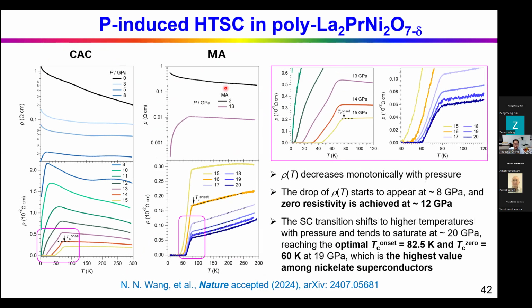Okay, then we measured the praseodymium doped 327 polycrystal sample. The measurement is similar, quite simple. We measured two samples with the cubic anvil cell and multi-anvil cell, and the result is very reproducible. For this doped sample, we start to observe the resistivity drop around 8 GPa, and we reach zero resistivity around 12 GPa, and the transition also moves up. Finally, above 18 GPa, the transition almost doesn't change much, almost saturated.